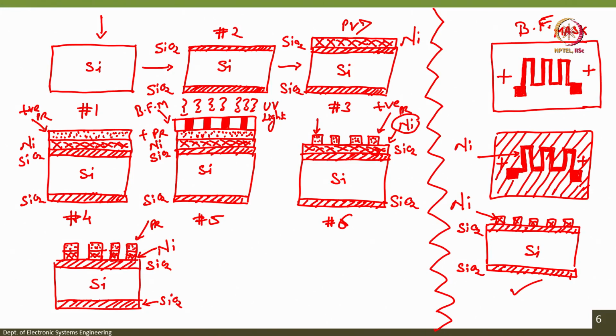So, now the next step is you dip this wafer in acetone. If I dip the wafer in acetone, acetone is a stripper for the photoresist, it will strip off the photoresist. Okay. So, photoresist will get stripped off, it will get removed from the wafer, and after dipping this wafer in acetone, what will we have? We will have only nickel left, because acetone has stripped off the photoresist.